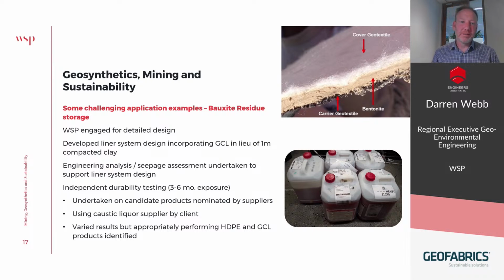And we went to an independent durability testing regime for the GCL and the geomembrane, in the same type of process we spoke about earlier. And that was undertaken on candidate products that were nominated by suppliers, and those suppliers nominated them with an understanding of what the service conditions were, and they nominated what might be called high performance geomembrane and GCL products. And the testing was done with liquor samples supplied by the client. You can see the samples of the liquor in the photo on the bottom right.